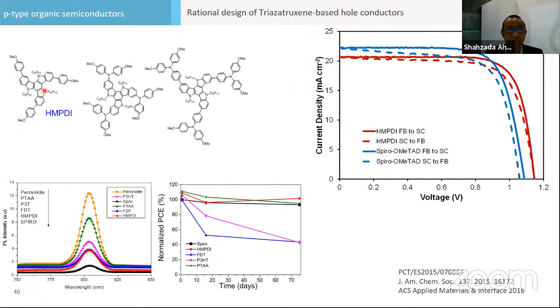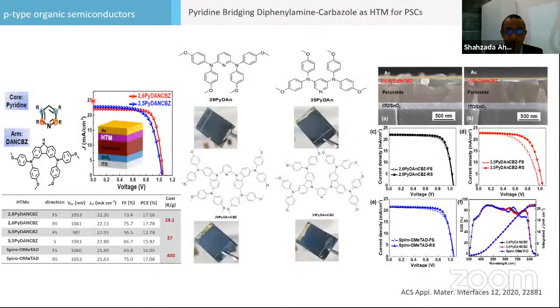The one benzene ring is connected with three indole units, and it was more efficient than Spiro. Currently, we're also studying carbazole based ones, and we are changing the position of the sidearm, because the interface is very important. By changing the position of the sidearm, we can modulate the efficiency and performance of the devices. This new type of carbazole based one, this is a pyridine based only. This doesn't work very well, but when we put a carbazole group, the film is more uniform. You can see on top of the perovskite, a more uniform film, and it works very well, giving you 18% efficiency.